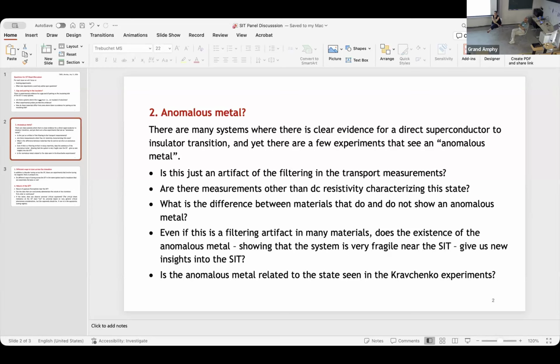The question is, this is the way we explain the insulators. What's the difference between this metal and the insulator? Why do some systems show this metallic behavior and others go directly to an insulator, or in between have finite resistance or very large resistance? If you have an insulator with superconducting percolation, you have no coupling between the islands, so you're limited by the phase stiffness of your islands, which is not the case if you have a metal. If you have a metal, you're limited by the coupling strength in the metal, which is a really different picture.